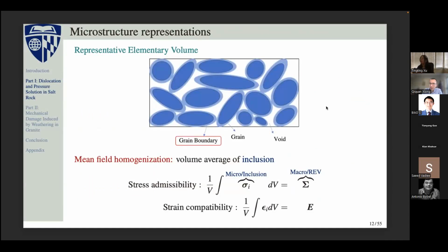So here, with the understanding of these two deformation mechanisms, here is how we pick these microstructural representations. In this representative elementary volume, instead of just choosing the solid phase and the void phase, on top of this grain and the void, we also choose the grain boundary as the third phase. So here is a sketch of it, and we will have the mean field homogenization scheme.